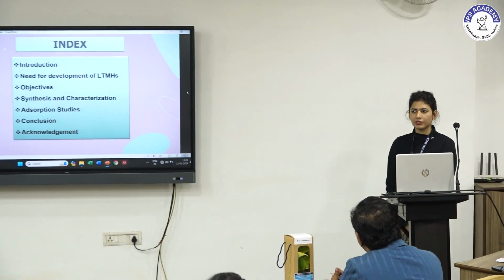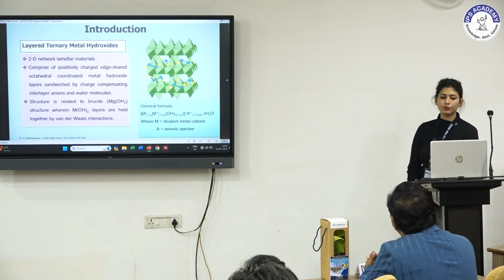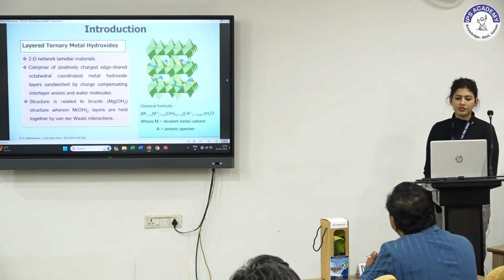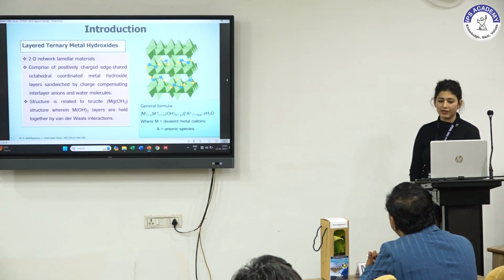The contents of my presentation include the introduction about layered ternary metal hydroxides, the need for development of LTMH, the objectives devised, the synthesis and characterization, followed by adsorption studies of the material, the conclusion drawn and the acknowledgement. Layered ternary metal hydroxides are 2D network lamellar materials comprising positively charged edge-shared octahedral coordinated metal hydroxide layers sandwiched by charge compensating interlayer anions and water molecules. Their structure is related to the brucite structure, which contains Mg(OH)2 octahedra, while in LTMH the M(OH)2 layers are held together by van der Waals interactions.